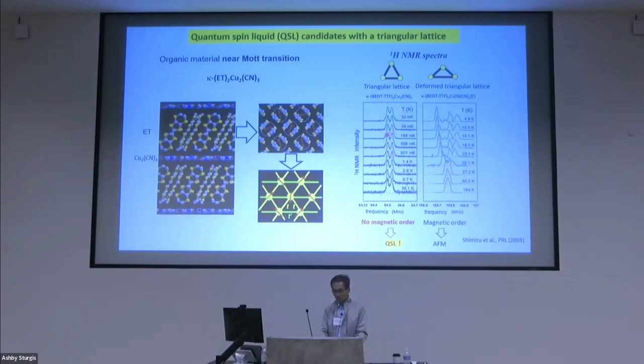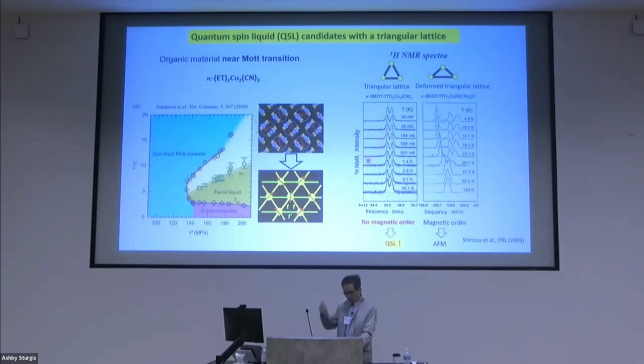The exchange interaction of this material is 250 kelvins. Down to low temperatures, well below the order of magnitude of the interactions, the spin is paramagnetic. So we think that this is a spin liquid material. Okay, this is a phase diagram. At ambient pressure or low pressures, the system is insulating, and maybe a spin liquid. At higher pressures, this system shows Mott transitions. So this material is close to the Mott transition.